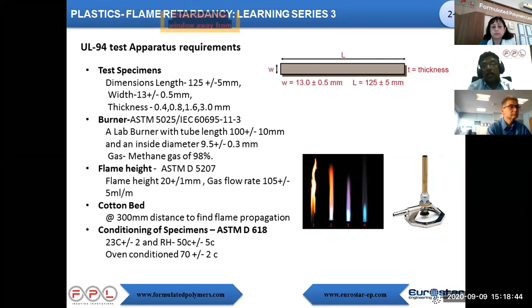For HB and V0 vertical burning, we have to follow a specimen length of 125 mm and width of around 13 mm. We have some tolerance of 0.5 mm. Then the thickness of the specimen is also important. It should be around 3 mm for horizontal burning, and in the vertical burning case, it should start from 0.025 and go up to around 13 mm. So the maximum thickness should be 3 mm for all UL 94 tests.